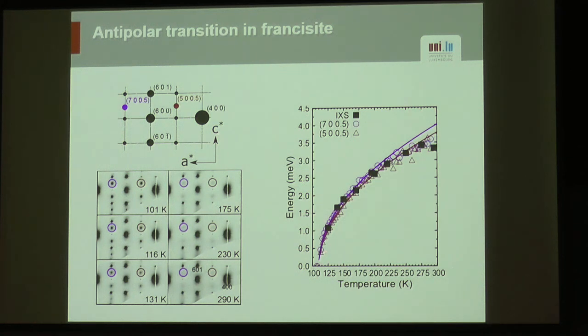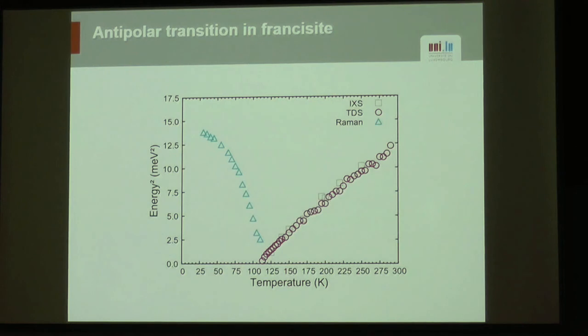So this is what the final result looks like. The black squares here are the real inelastic spectra that you've seen before. And those red and blue data points are what has been extracted from the diffuse scattering intensity, rescaled to match those values. You see that the rescaling works really nicely and can be followed down to quite low energy. So in summary, we really have the soft mode, as we expected, in Raman spectroscopy and in the inelastic X-ray spectra. If I put everything together and plot, as we usually do, the energy squared as a function of temperature, I get something like this.